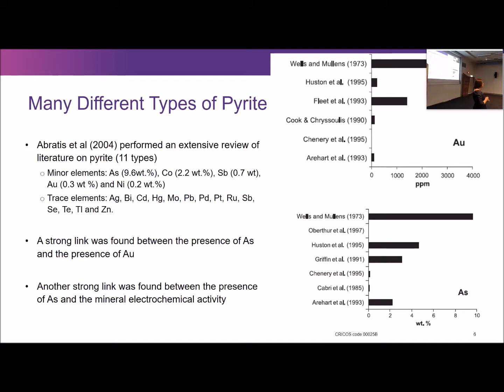Abraitis in 2004 did a very exhaustive review and found 11 different types of pyrites. Doyle and Mirza did electroactivity surveys of pyrite and looked at 12 different types. What Abraitis found is that you have a huge variation. You have some minor elements, including gold and arsenic, as well as a great number of trace elements such as silver, antimony, bismuth, etc. What was found is that there is a very, very strong link between the presence of arsenic in the pyrite and the presence of gold. So if you are looking for gold and can't find it, look for arsenic, and you will likely find gold there. That's a very strong link. Another very strong link was found between the presence of arsenic and the level of electroactivity of that pyrite.